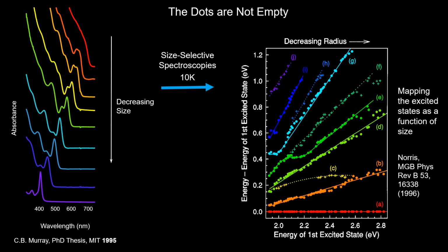And so the small particles on your right are kind of like atomic properties. You can see these harmonics pretty well spaced together, and as the size gets bigger, they sort of get closer and closer to each other. But right around there, they start to deviate from that behavior. And as spectroscopists, we call that an avoided crossing. There are two transitions that want to cross. One flattens out, the blue one wants to go flat, but it's avoiding the other one.